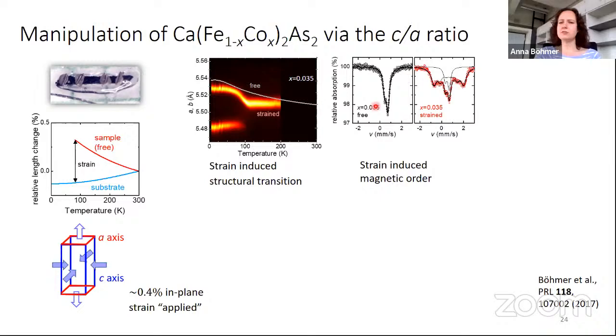We also used a different technique, Mössbauer spectroscopy. You don't really need to understand it. It means we see two very different spectra for a free sample compared to the sample on the substrate here. The sample on the substrate has this complicated spectrum, and it means it's magnetic. There is magnetic order. These moments have ordered.